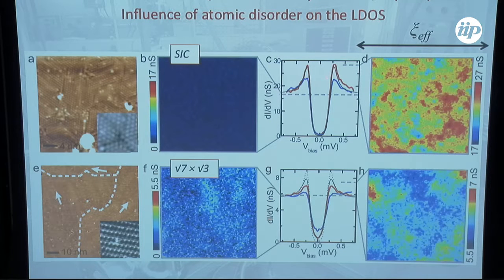And so what you see immediately is that while the gap is quite constant everywhere, the height of the quasi-particle peaks varies very rapidly on atomic scale. And this is something unusual for superconductivity, in which, as all of you know, we do not expect variation of the order parameter on scales shorter than psi, which in this case, I will demonstrate to you, is about this size. Okay? In the a little bit less dense square root 7 by square root 3 situation, it is even worse. You get not only very strong damping of the quasi-particle peaks, but you also have a filling of the gap. Okay, and this is something really unusual in classical conventional superconductivity.